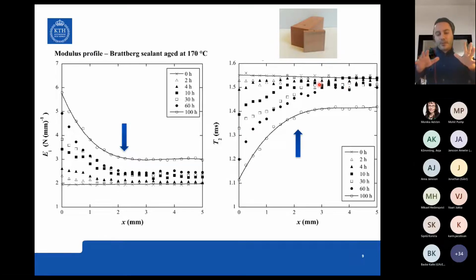So it means that the material is stiffer compared to the bulk. So we haven't yet done a full quantification of relaxation time to mechanical behavior, but it's still in the phase of the trends are the same. But the future research definitely should be that we should try to quantify relaxation more with mechanical data. Since one thing which is totally widely accepted in the nuclear industry is mechanical testing. So a breaking load test or a stiffness test is widely more accepted in the industry. So we need to start to benchmark relaxation times more to that.